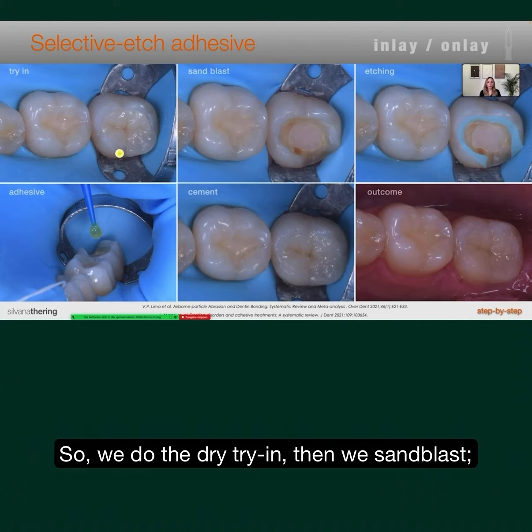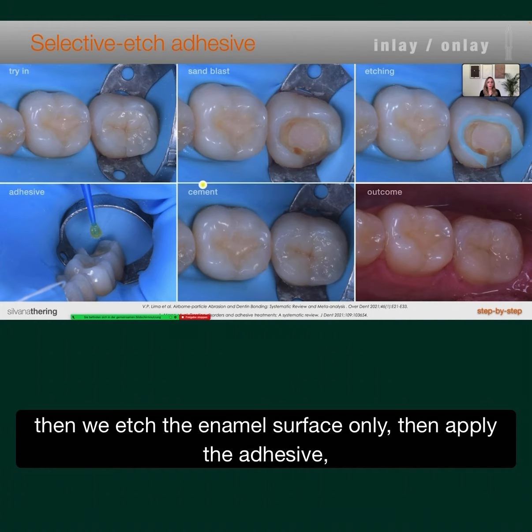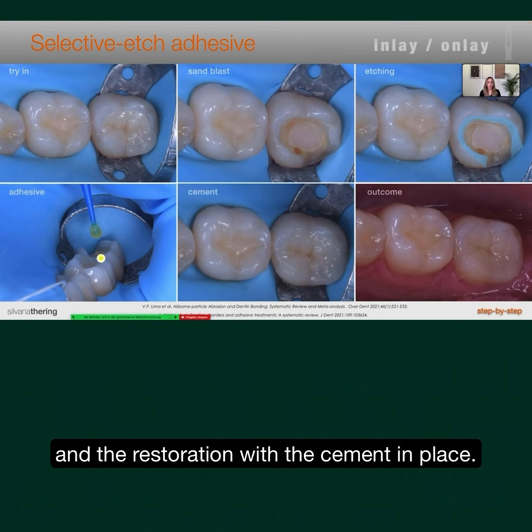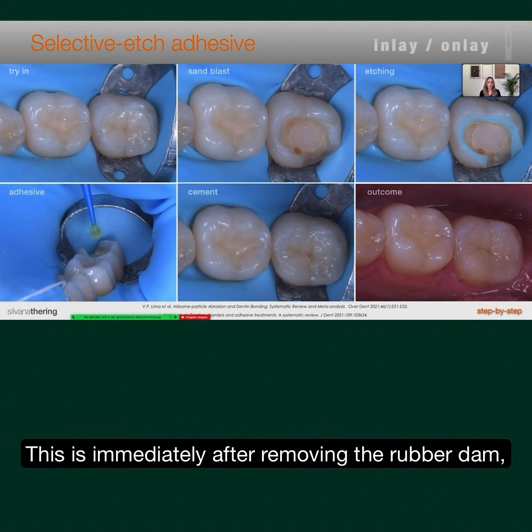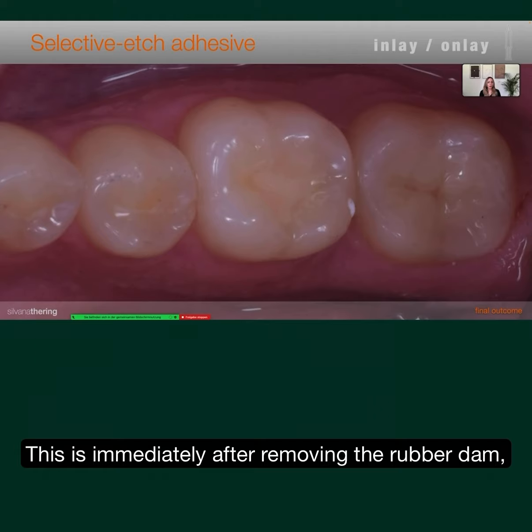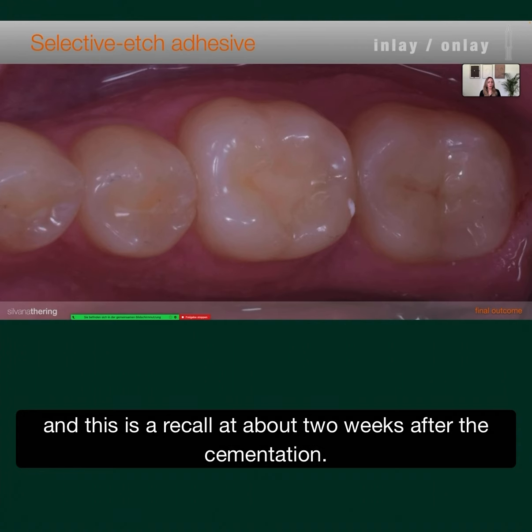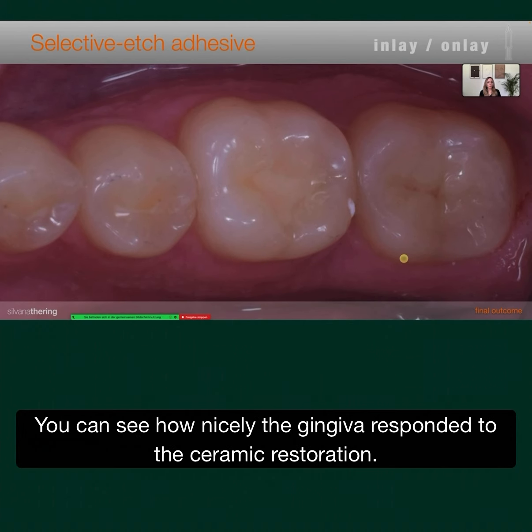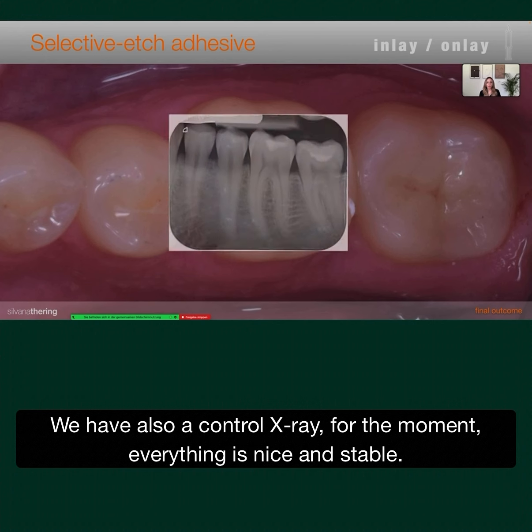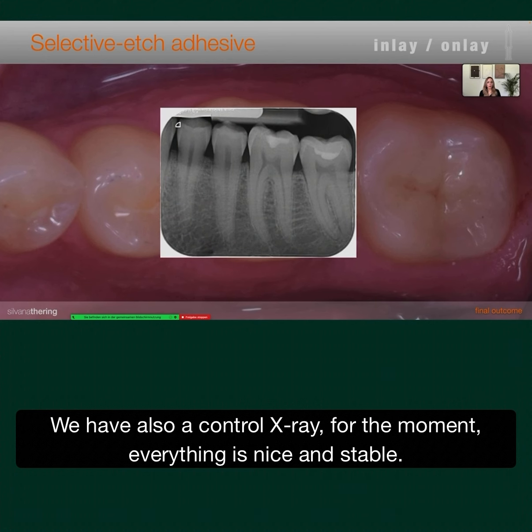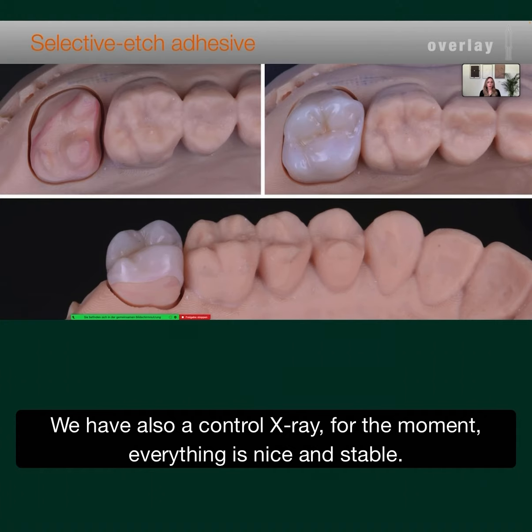So we do the dry try-in, then we sandblast, then we etch the enamel surface. This is where I applied the adhesive, and the restoration with the cement in place. This is immediately after removing the rubber dam, and this is a recall at about 2 weeks after the cementation. You may see how nicely the gingiva responds to the ceramic piece. And we have also a control X-ray. For the moment, everything is nice and stable.